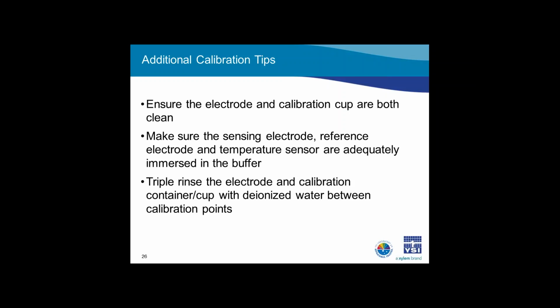Lastly, as a best laboratory practice, triple rinse the sensors and calibration container with deionized water between calibration points. Before continuing with the calibration, make sure to shake off any excess DI water or dry the sensor and container with a chem wipe before placing it in the next buffer. When drying the sensor with the chem wipe, be sure to blot it so you don't accidentally damage the sensor.